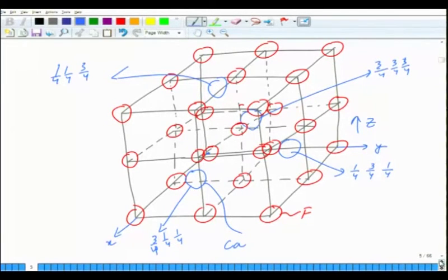So now this calcium fluoride structure is followed by a variety of materials. There are a lot of fluorides which follow this structure. So CaF2, but you also have ZrO2, UO2 and various other oxides follow this structure, okay. So these are all ionically bonded solids. Now, another compound in this series is called antifluorite.